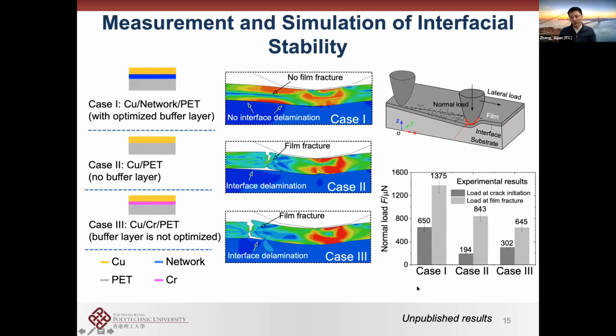And if we measure this unpublished result, you will find that the reason why it has this high stability is because this case one is our PAMD made material. They have a very high load at crack initiation. That means it's very difficult to form cracks. And it also has a very high load at film fracture. That means once the cracks are formed, they are very difficult to fracture, right? So these two properties ensure the high stability of our PAMD made polymer.